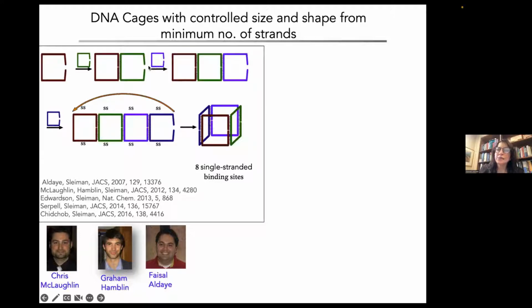And we can continue to do this. Let's make the green strand here complementary to the backside of this blue strand to cyclize. Then finally, we introduce the fourth strand, this dark blue strand here. Again, the light blue strand cyclizes on the dark blue strand. Now we're ready to close the cube. We design this strand here to be complementary to the backside of the first strand shown right here, so that it closes upon itself and creates this cubic shape.